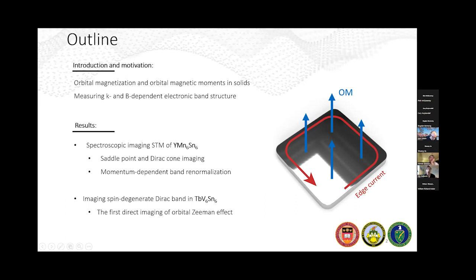And then I will also tell you how we can investigate how these evolve or renormalize as a function of magnetic field. Not many techniques can measure the electronic band structure while being able to apply a magnetic field externally and essentially change the electronic band structure by that. And this is one of the bread and butter of STM.